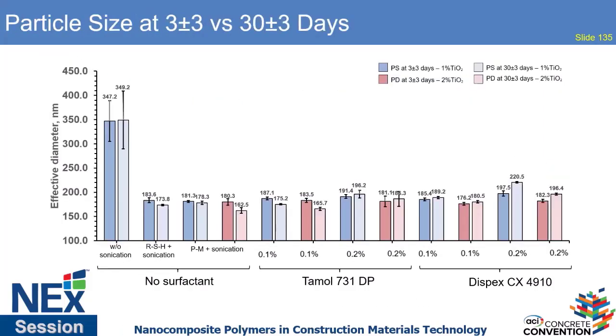Furthermore, we measured the particle size using dynamic light scattering, and we did it at 3 and 30 days for all the samples except the samples that were not sonicated. We have seen a particle size roughly around 170, 180 to 190 nanometers, and between 3 days and 30 days there was not a significant increase in particle size. And also the first sample is showing that there is not a significant increase in particle size.